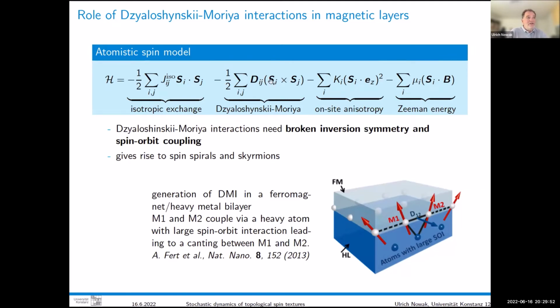The Dzyaloshinskii-Moriya interaction is a cross product. It appears only under certain conditions, and it has something to do with the inversion symmetry of the crystal that you have. For a thin film, normally the inversion symmetry is broken at the interface. And if you have a lot of spin-orbit coupling, for example an interface to a heavy metal like platinum or so, then you will get some Dzyaloshinskii-Moriya interaction at the interface.